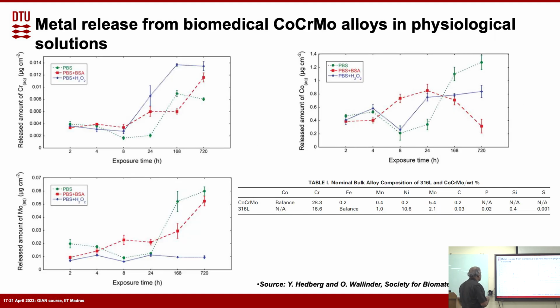And this is another thing, which is showing the metal release from the biomedical cobalt chromium molybdenum system. And again, I think the interesting part is the chromium release here, because chromium is one of the metals you don't want so much. You can see that with exposure time in this biological media, the chromium release is increasing. It goes up probably 3 or 4 times with exposure time. I don't have the data here on exactly how much chromium is allowed in the body, but that's a good thing to look at. But you can see that it is released from this cobalt chromium molybdenum alloy.